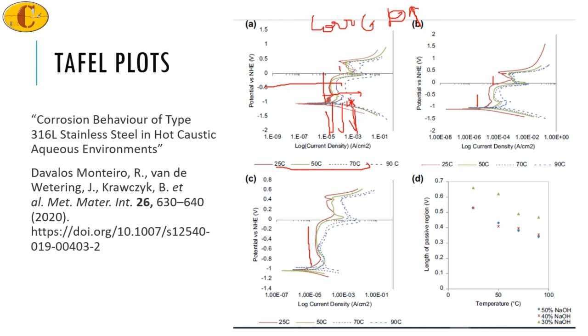The shape of the plot will change with respect to the concentration of the sodium hydroxide. The shape of the plot change can be seen. So we know that there is some effect. But chemically, it means that if you see here, the height is different in the lower NaOH. So in 30%, you have a larger passive film region, and in the higher concentration you have a shorter passive film area. A shorter passive film area may mean that the chromium oxide film is going to pit early.